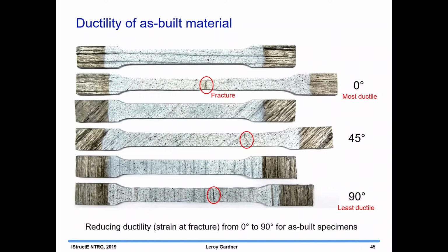So these are pairs of coupons before and after testing. You can see the fracture in the middle of the coupons. The 0 degree directions, where you're pulling in line with the printing direction, are the most ductile, whereas the 90 degree ones, where you're pulling across the layers, were the least ductile.